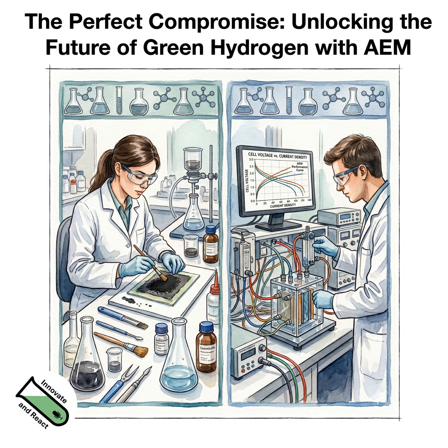What is PTL? In this case, it's a porous transport layer. For our porous transport layer, in the PEM systems there are often used titanium non-wovens. And in this case, we use a porous nickel or porous stainless steel non-woven as our substrate for our catalyst layer. Okay, so you have the membrane in the middle, and then you have this porous transport layer on both sides, and then on each of those sides you have the anode and cathode catalyst material. But the catalyst, of course, is still sitting at the membrane. Yeah. So it's membrane, catalyst, and then this porous transport layer. So it is like doing it directly on the membrane.